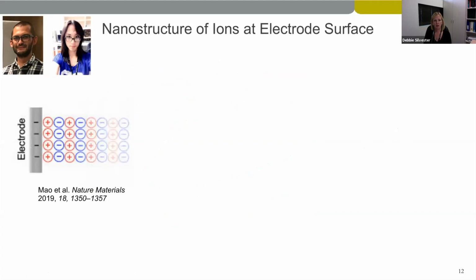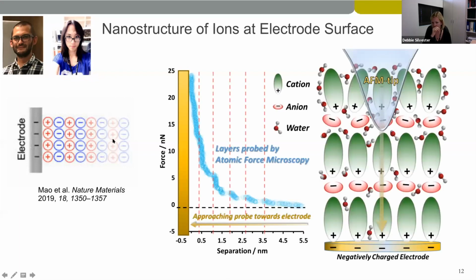And so together with my postdoc Jenny, Simon was probing the structure of the ions at the electrode. As I mentioned before, we have a negatively charged electrode. In the case of oxygen reduction, we bias negatively, so it's the cation that builds up on the electrode surface. And then we have our alternating layers of ions.